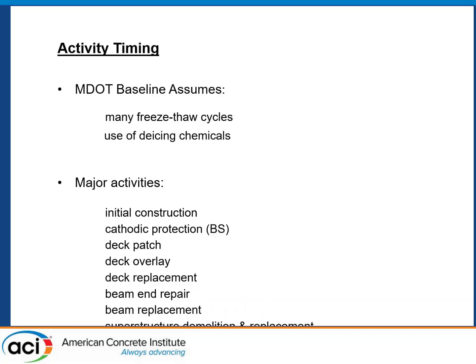Now, the MDOT schedule assumes a fairly aggressive environment. There are a large number of freeze-thaw cycles, as well as a heavy use of de-icing chemicals. But there are a large number of major service activities. Initial construction, for unprotected steel, we have the cathodic protection, deck patching, overlay replacement, beam end repair and replacement, and then finally superstructure demolition and replacement.